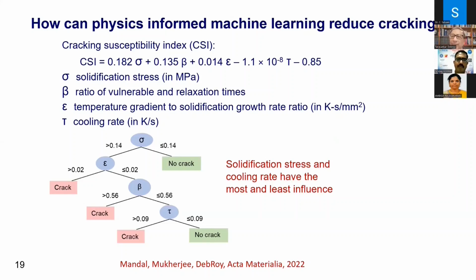So how can we relate this index with the micro cracks that are being developed? The index is affected by solidification stress, the ratio of vulnerable to relaxation times, the temperature gradient to solidification growth rate or morphology factor, and cooling rate. So one has to do calculations of these four quantities in order to calculate a value of CSI. And once you have done that, you have a pretty good confidence of whether or not a sample is going to crack before you actually make a part. That's the beauty of it. You don't have to spend your time, spend your money, and then find out it's cracking. You can do that before, virtually. Okay. No empirical trial and error.